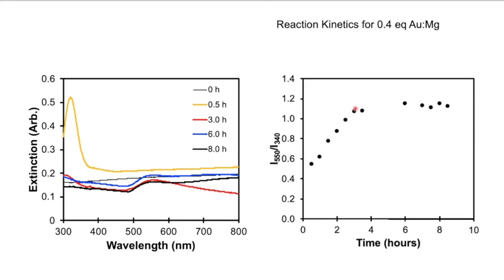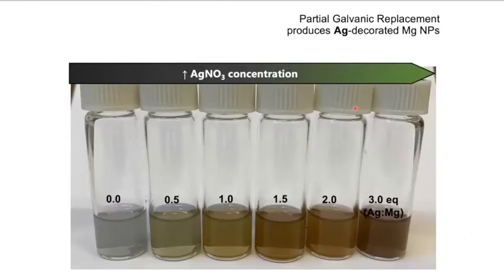And again, this is most likely due to the presence of that oxide that creates a big barrier. Once the oxide is pitted a bit, the reaction goes, but it takes time to get there. We've been able to do this with any metal you can name. Essentially, it's just so easy. Indeed, because there's such a driving force. So here's an example for silver. Again, just the silver plasmon resonance that comes through.